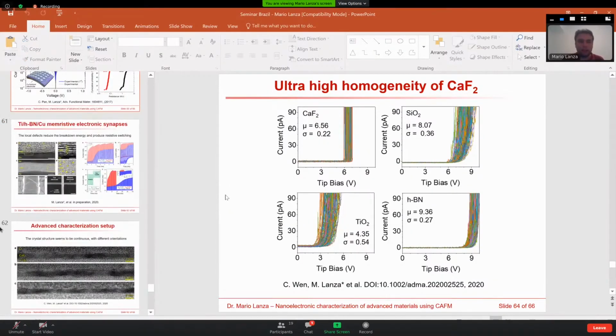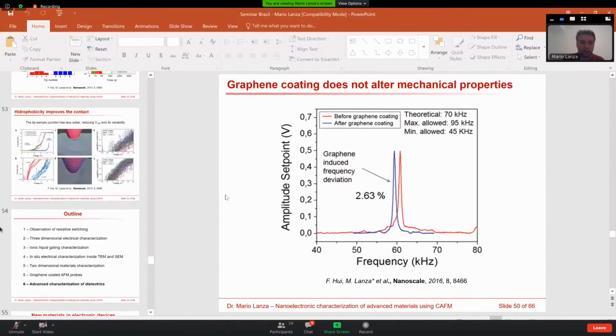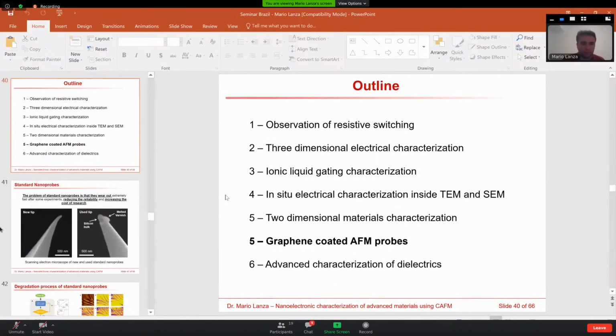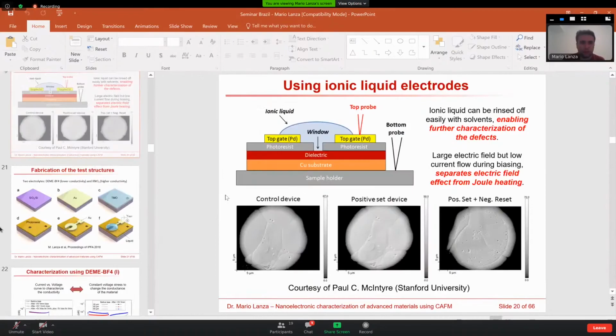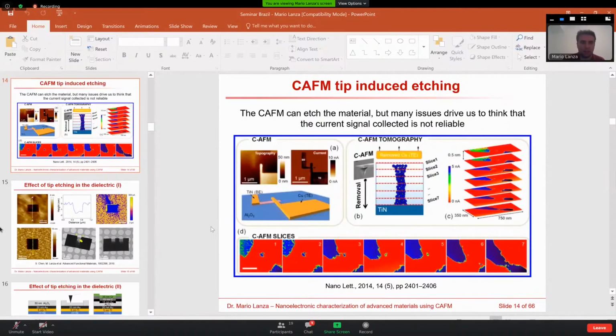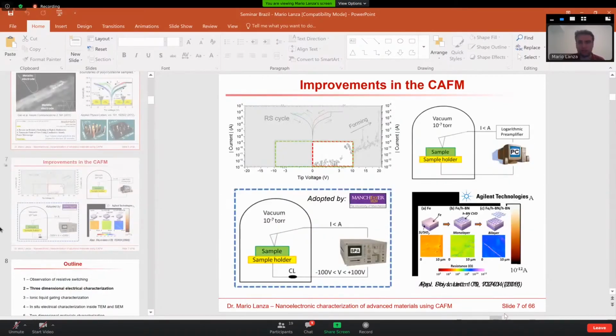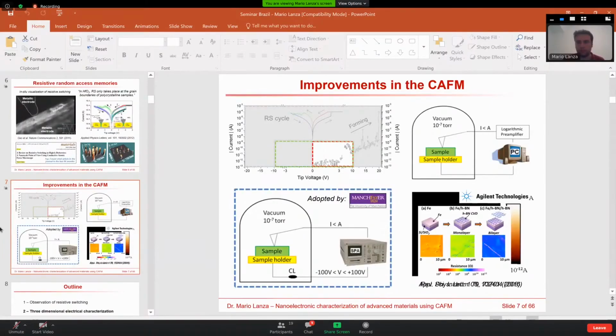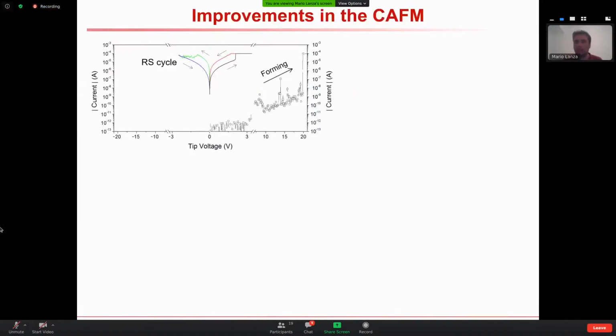And about the first question, the size of the conductive filament, there is something I should highlight. As you can see here, when we create the conductive filament at the beginning, we need to apply a current limitation. If we don't apply a current limitation, it doesn't matter if you make the stress at the probe station or with the CAFM. You need to apply a current limitation.